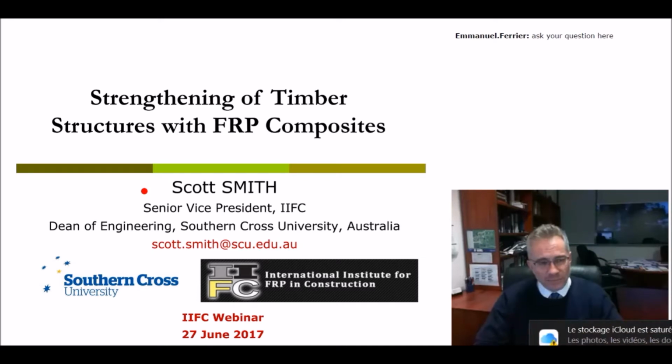If we have experience with bond of FRP to, say, concrete joints, we would know that the bond strength is limited. It's limited by the strength of the concrete. And the debonding, which is the primary failure mode, occurs in a rather brittle manner. Hence my interest in anchors.